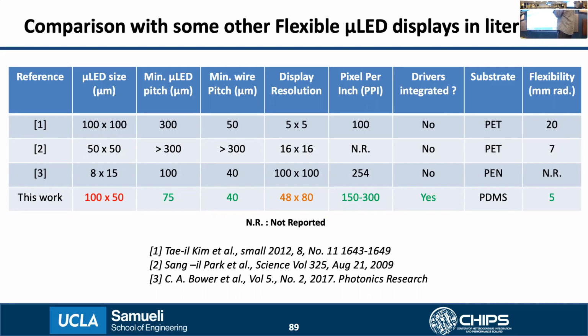We can also demonstrate a PPI between around 150 to 300. And this is also the only work where silicon CMOS driver ICs were integrated on a flexible substrate as part of the display. However, more work has to be done in integrating much smaller LEDs because in the future we wish to integrate less than 50 cross 50 micron square devices and also build larger displays to more than 100 cross 100 arrays.